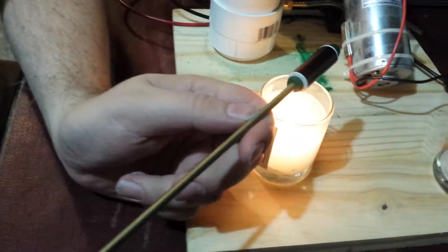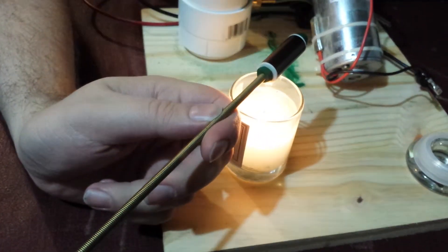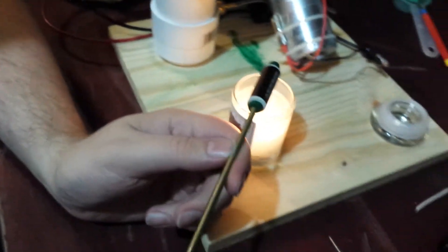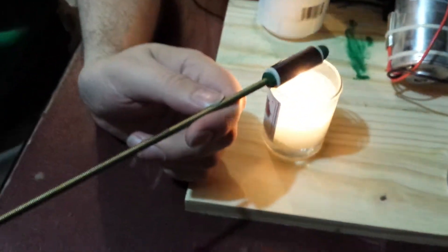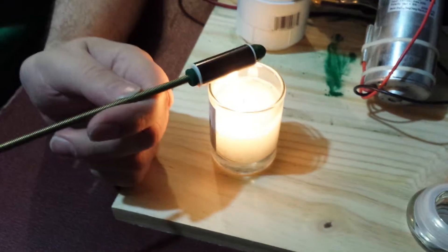It doesn't need to be too long. Try to concentrate at the ends a little bit longer because they have heat drawn away from them due to the washers, and they don't get covered as well sometimes.